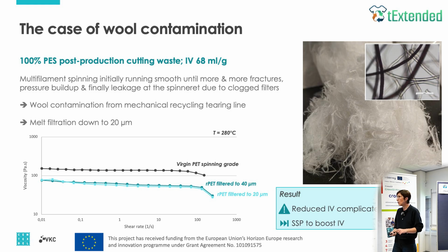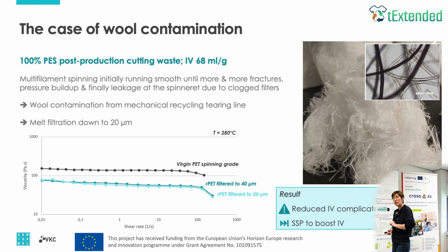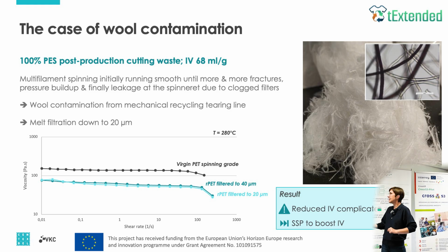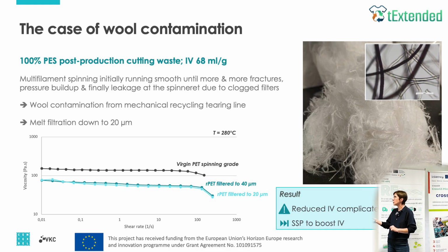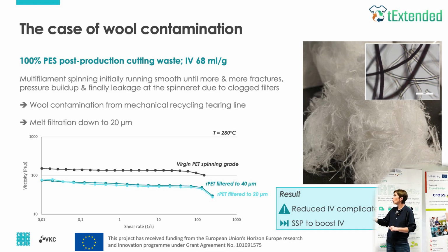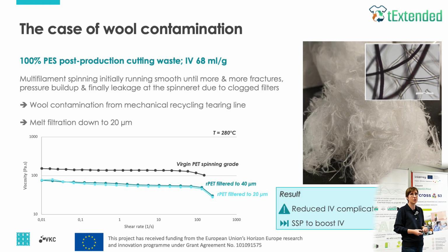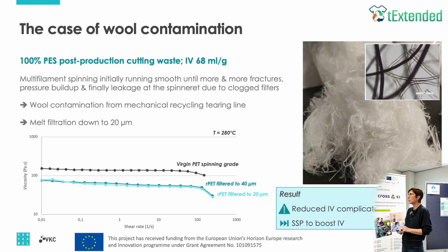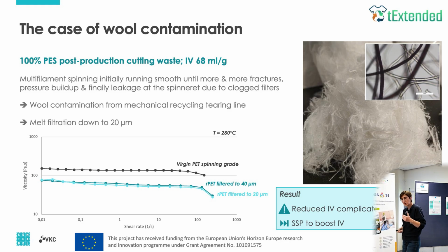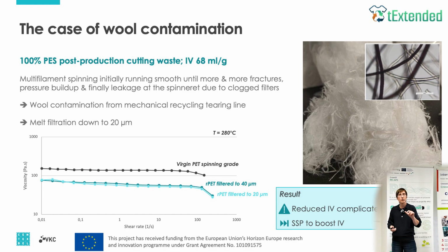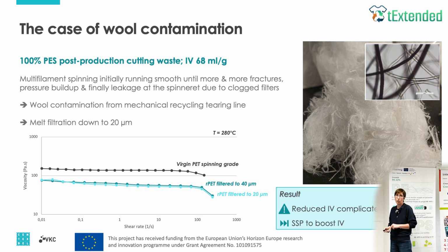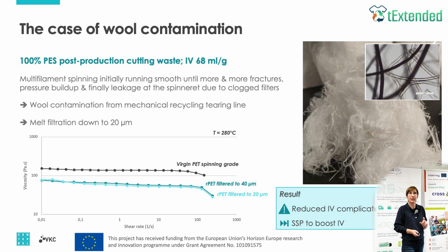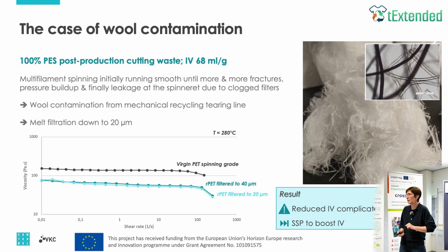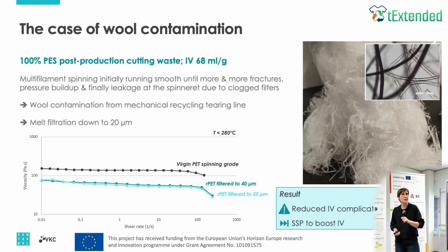Just as an example, I say we need some kind of monomaterial waste stream. This is 100% polyester post-production waste. The IV, you see here, was quite good, so we really believed this was a material we could process back into fiber to fiber. But when trying to do this, and looking further into detail, you see here that black fiber appearing. This is definitely not polyester, so there was some wool contamination in our material. And even a small fraction of this wool contamination was causing a lot of problems and was blocking our filters.